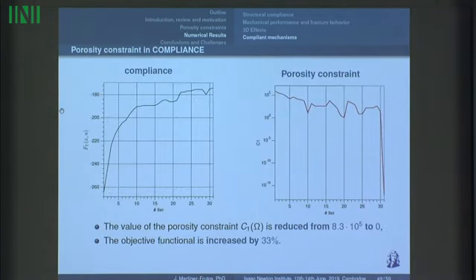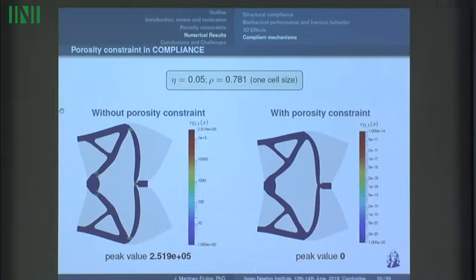We see that these results correspond to these two designs, and here we can clearly see that we can eliminate the porosity that appears in regions which are close to being hinges, very weak regions, and these regions are increasing thickness to eliminate this porosity sensitivity. The consequence is that the output displacement is not as high as the displacement that we had with the design without this porosity constraint. So this is a small drawback of this problem, but we can control it by modifying this parameter.